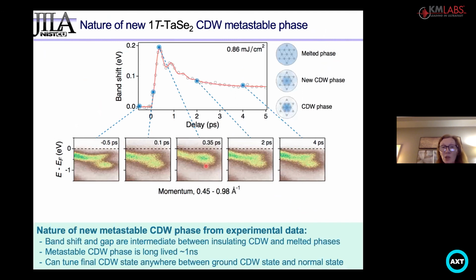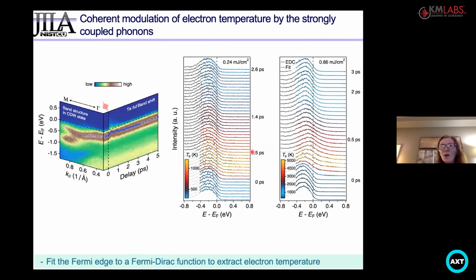And in fact, we can look at that with angle resolved photoemission. We can see that sure enough, in this intermediate state, there is a band gap, so it is a charge density wave state. We also learned other very surprising things about the material.